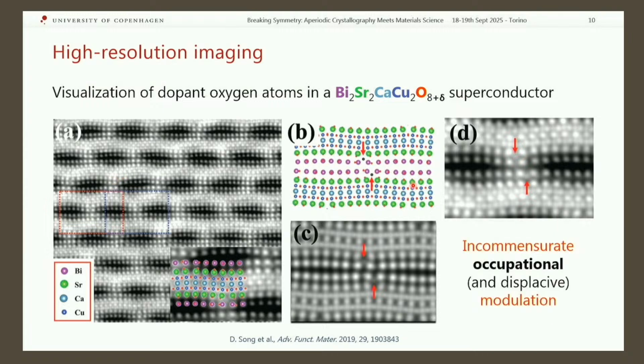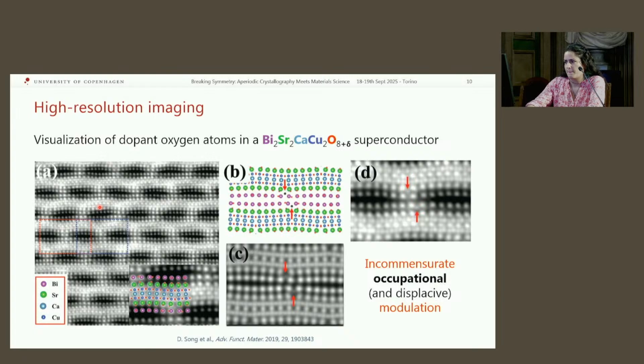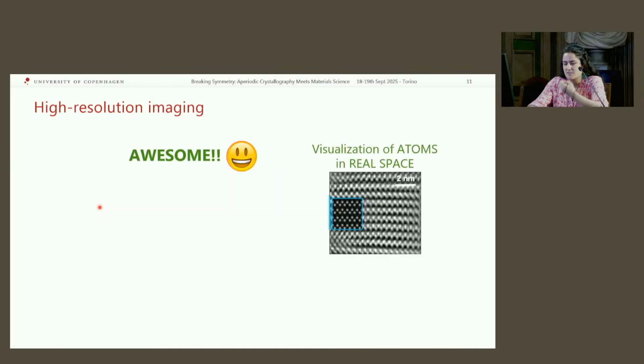So we have occupational modulation due to the presence or absence of the oxygen, and then displacive modulation of all the other atoms. And if you count the dots here, you will see that these waves are not periodic compared to the lattice of the crystal structure. So here we are really seeing the atoms with our eyes, and that seems a perfect way to determine the structure, right? So microscopy is really powerful.